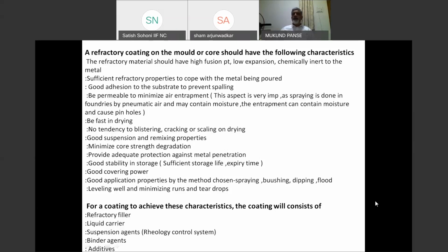The coating should be correctly applied on a sand wall. The refractory material should have high fusion point, low expansion, chemically inert to the metal, sufficient refractory properties to cope with the metal being poured, good adhesion to the substrate. The coating should get adhered, it should not spill out, it should not spall, it should not form cracks, blisters. It should dry fast. Blistering, cracking and scaling should not happen.